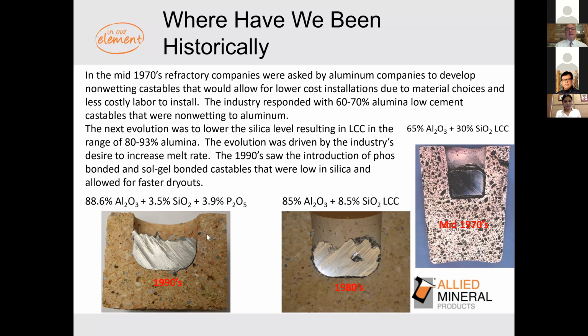And then in the 90s, we developed in our industry phos bonded castables and eliminated the low cement castable, the calcium aluminate cement bonding that held all the particles together and gave it strength. It gives the refractory excellent strength, but it also adds brittleness to the refractory. It's not quite as thermal shock resistant. There's dehydration of the cement in a castable. There's 3 or 4 critical dehydration points that you have to be sensitive to during the dryout. So your dryout periods are longer, which means handing it back to production for a reline or repair takes longer.